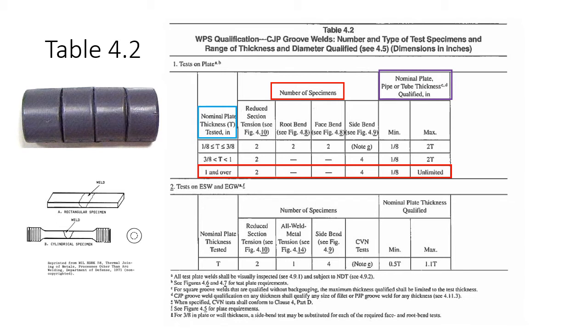Table 4.2 tells us, okay, so for WPS qualification, complete joint penetration groove welds, the number and type of test specimens and range thickness and diameters qualified. So we're going to start with that blue square I've got under nominal plate thickness. Let's say our test plate is 1.25 inches. So we go to there, our test plate's 1.25 inches. It's going to tell us, the red square or rectangle of number of specimens is going to tell us, okay, we got to do 2 reduced section tension tests. So we've got that right there.